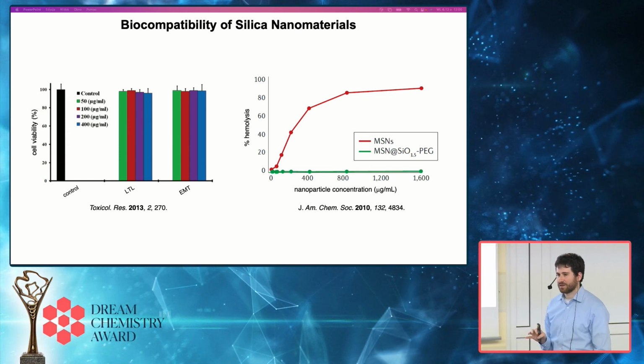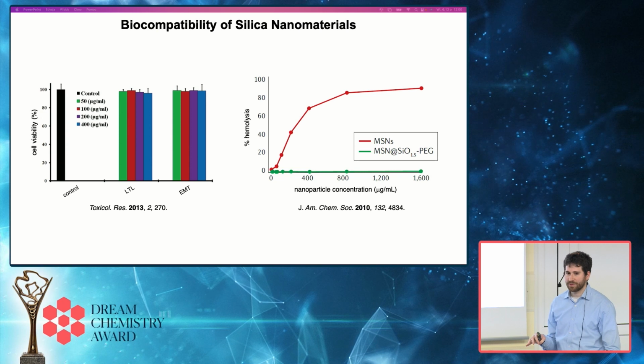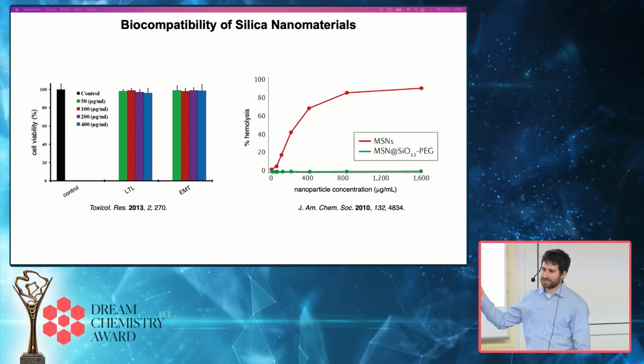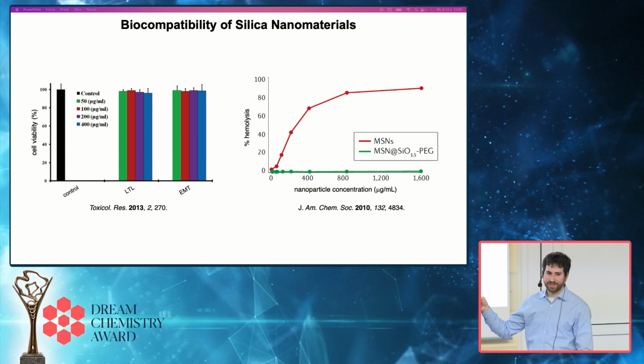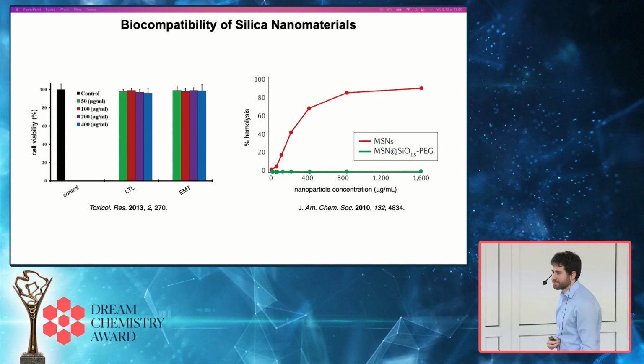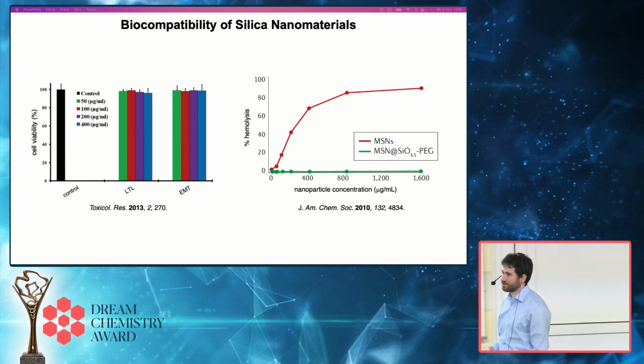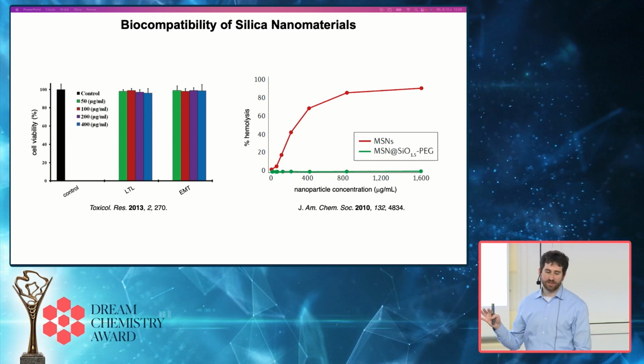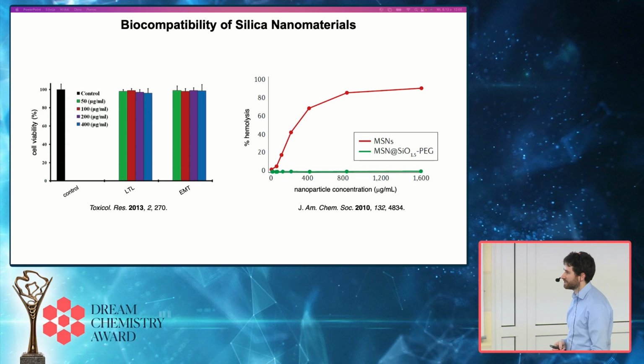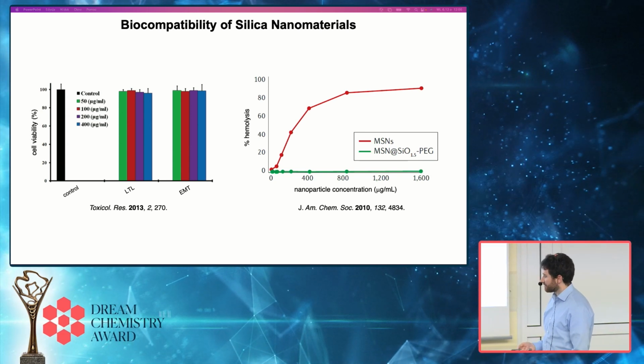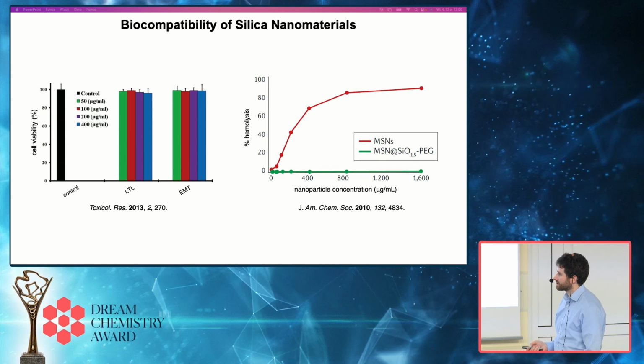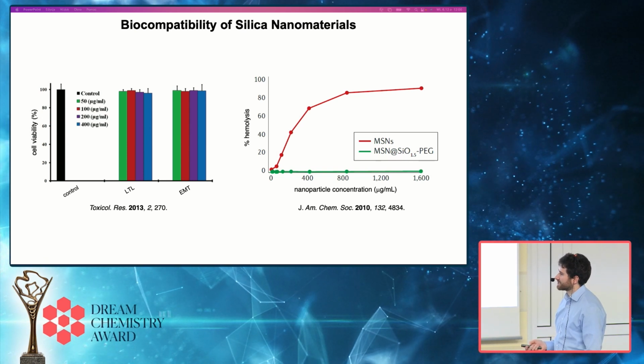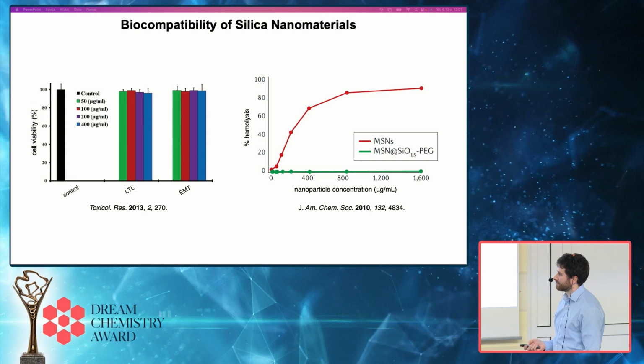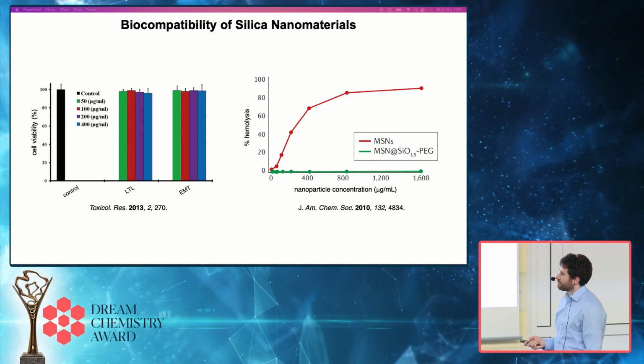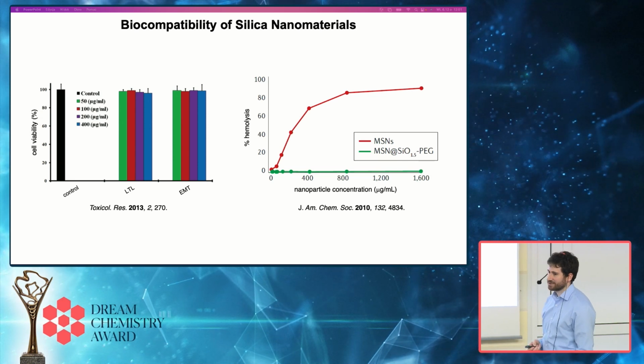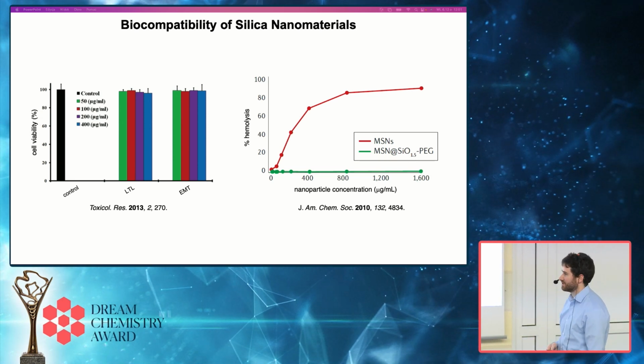The pure silica silica nanoparticles tend to not be very biocompatible. These silanol surfaces are really good at interacting with cell membranes and ripping them apart. So they'll generally have quite high cytotoxicity. This is known from a lot of literature related to developing silica nanomaterials for drug delivery applications, which is quite advanced. So different silica nanoparticles can have very different cytotoxicities depending on their structure. This is an example of mesoporous silica nanoparticles that were investigated for drug delivery applications. Again, in their native form, when you have a high concentration of silanol, it's very cytotoxic to red blood cells, and induces a lot of hemolysis.